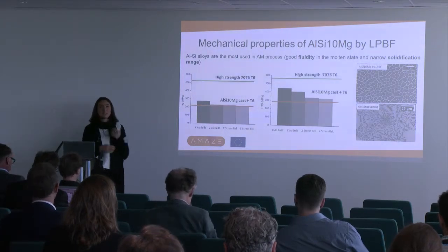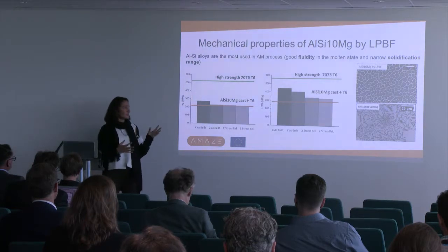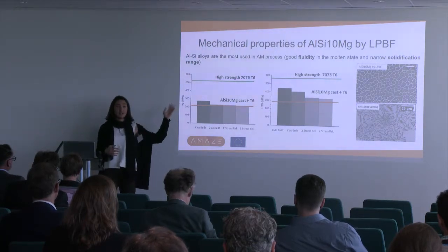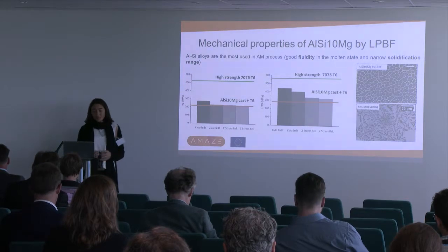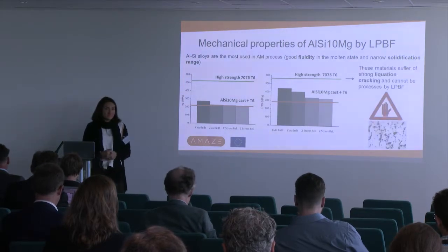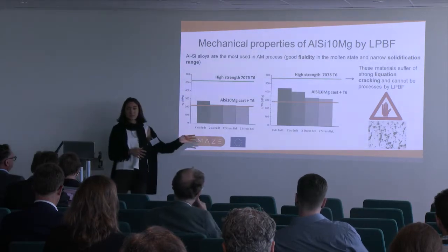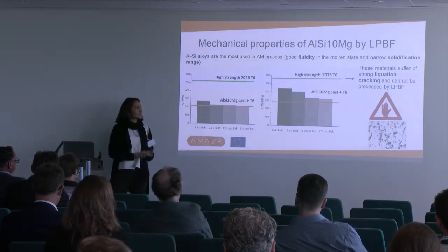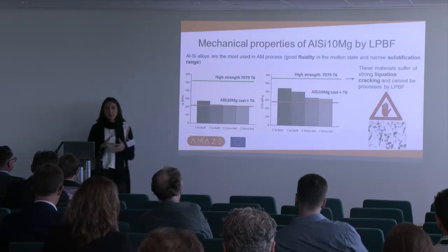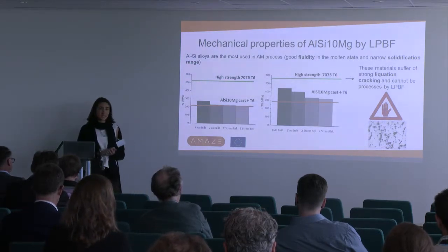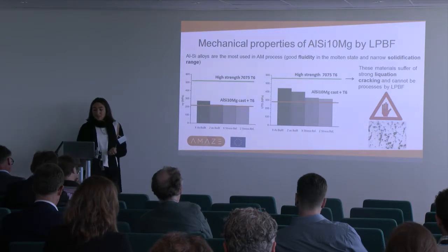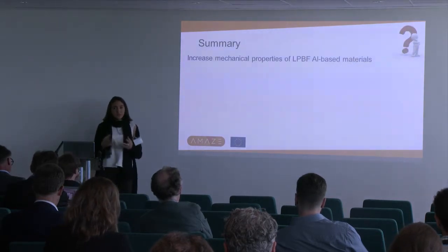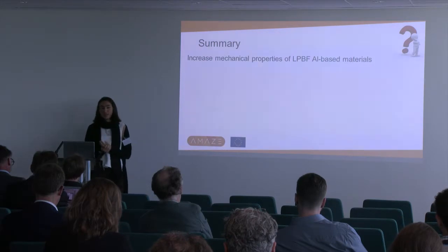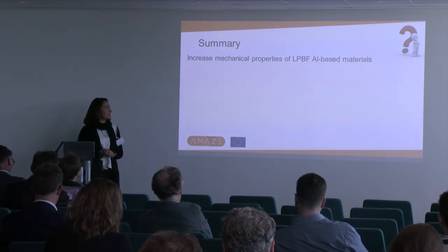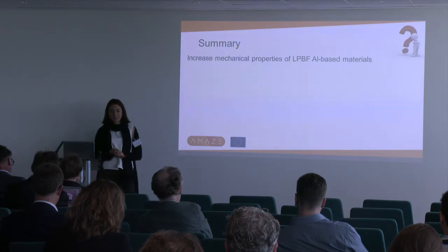If we look at high-strength aluminum alloys, such as the 7075 alloy, we can see that the mechanical properties are higher. And these alloys are, unfortunately, not processable by powder bed additive manufacturing because they strongly crack during the laser scan because of the residual stress and the liquation cracking phenomenon. So the goal was to find new materials that have higher strength for powder bed additive manufacturing processes.